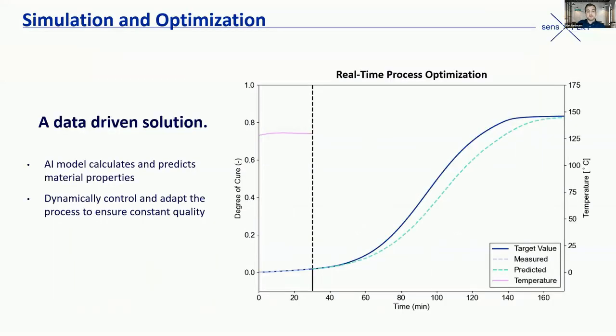And what this looks like is something like this. So continuing with that resin transfer molding example, that pink line is the temperature. That's all we're controlling. We've frozen the time here at 30 minutes. And so we can see that initial prediction of what our process is going to look like at this temperature, right? So we have our target is the dark blue. The predicted measurement at the completion is that green line.